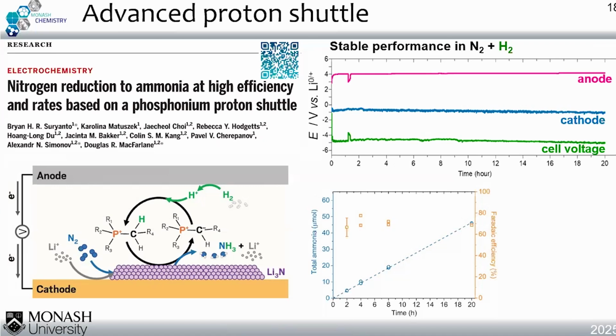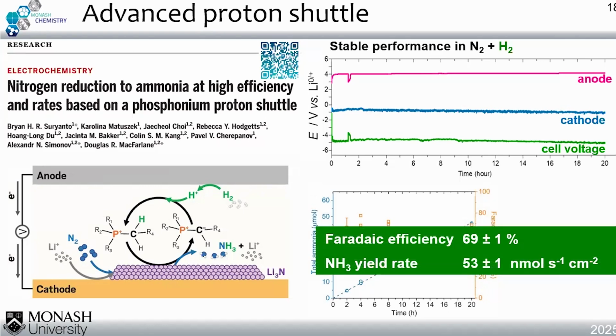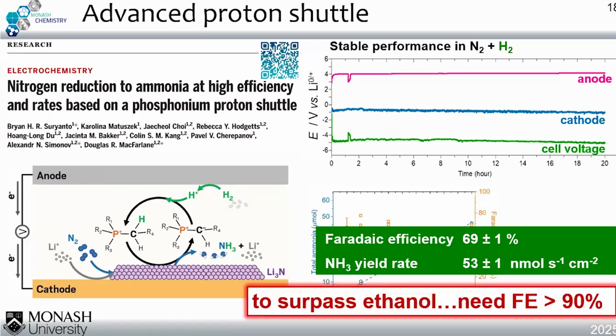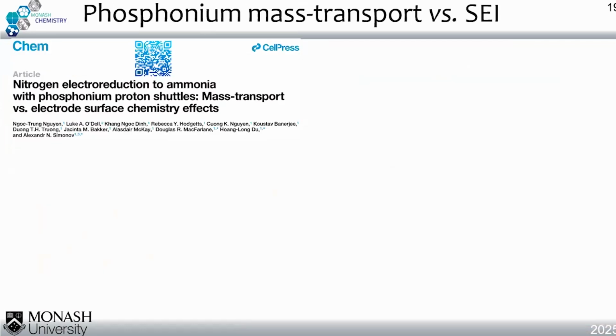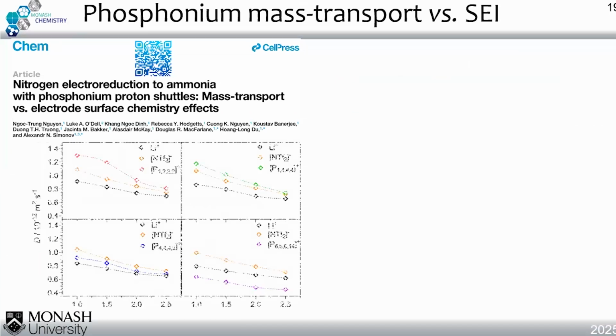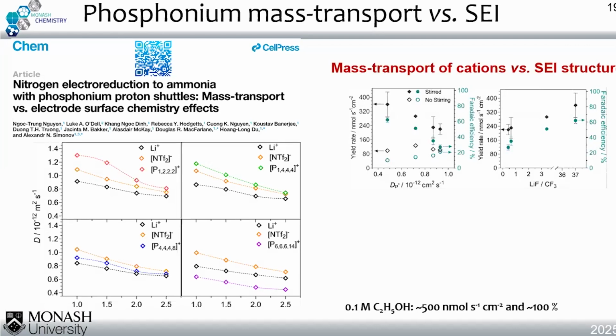Therefore, we add the nitrogen and hydrogen inside, and we could improve the performance, stable for 20 hours, and we can go longer. And then we can see the linear increase of the ammonia yield with the Faradaic efficiency around 70%. To surpass ethanol, we need to improve the Faradaic efficiency up to 90%. And therefore, we look into the mass transport because the phosphonium we use has a long alkyl chain and is very bulky. So we try to shorten the alkyl chain and hope that it's going to improve the mass transport and then improve the performance. However, the results tell us the opposite.